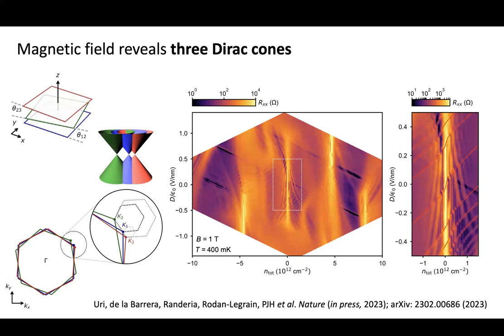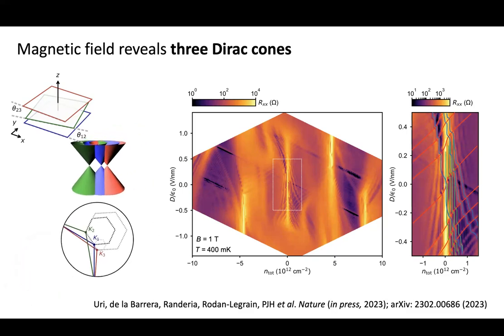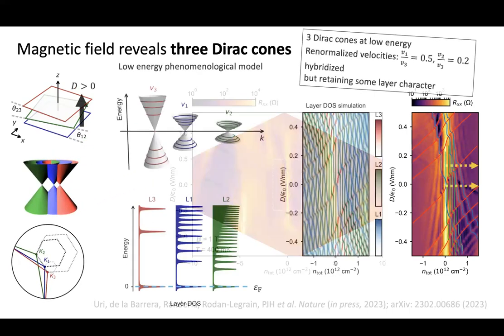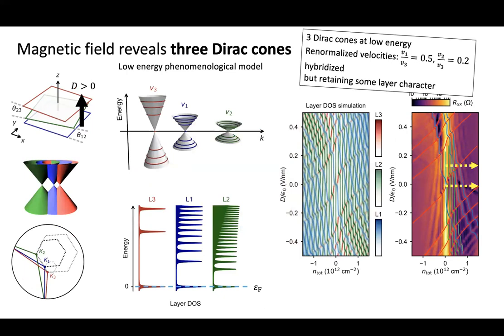You can look at this paper, which is about to come out, or look at the arXiv. So we have three sets of Landau levels, and I'm sorry, the lines don't come up very well here, but basically by looking at the Landau level crossings as a function of displacement and density, we can get, in a calculation, a pattern that matches those, and you can extract the ratio of the renormalized Fermi velocities. You cannot get all three, but you can get the ratios, V1 over V2 and V2 over V3. And you can see that they are different.